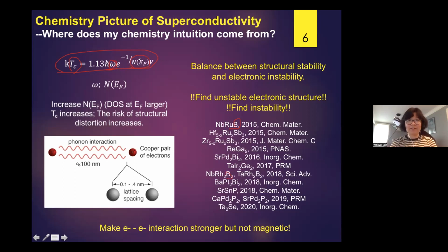And the second way is to try to increase the density of states near the Fermi level. But if we increase the density of states at the Fermi level, there is a risk that the compound may become unstable. So the goal is very simple: make a compound that has a very high density of states near the Fermi level, but at the same time the structure can exist. This is one way I always use to find new superconductors. I usually calculate the band structure and see if there is a flat band or a saddle point, and then I will find the superconductor. This is a very practical, very easy way to find new superconductors.